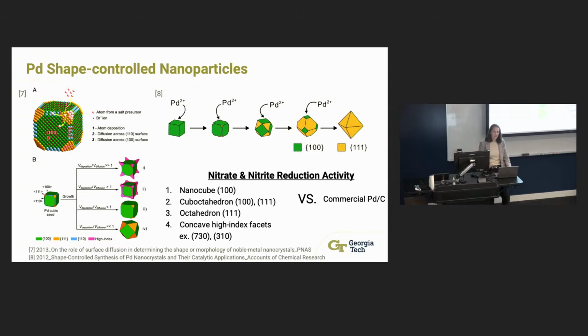An interesting thing is that the more challenging part, even more than growing the nanocrystals, was taking those extra surfactants and ligands off, because they sometimes end up binding to the surface. There are a lot of steps in taking them off, and a lot of exchange processes in the synthesis. Interestingly, that was the harder part than these crystals. And I definitely point to these two papers.